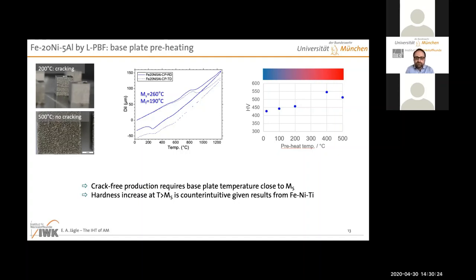However, on the last slide, I talked to you at length about how we need first to go below MS and then reheat, and then we get precipitation. Apparently in this material, something is going on even though we have never gone below the martensite start temperature. What is going on here? Why do we have a hardness increase at temperatures above the MS temperature?